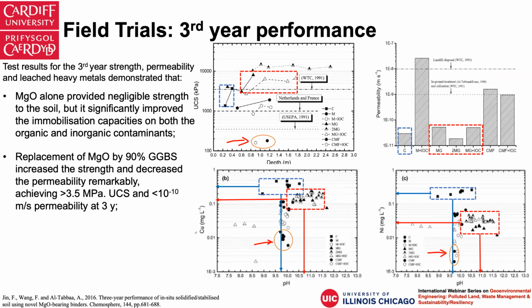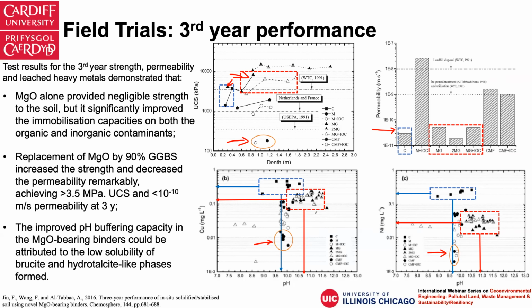You can include almost 90% of it. That increases the strength significantly. As we can see from these circles, it is even much higher than Portland cement. And the permeability is of the same order of magnitude. More importantly, the metal leachability is significantly reduced, almost 1 order of magnitude lower than the PC-based treatment. And the pH values stayed around 10.5 to 11, which is definitely much better than the PC ones.